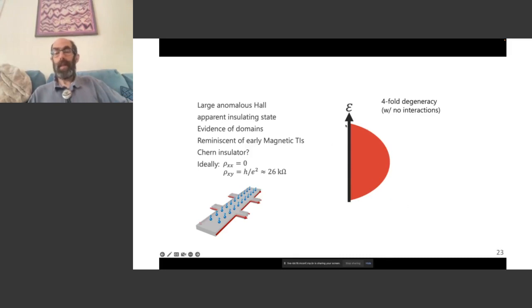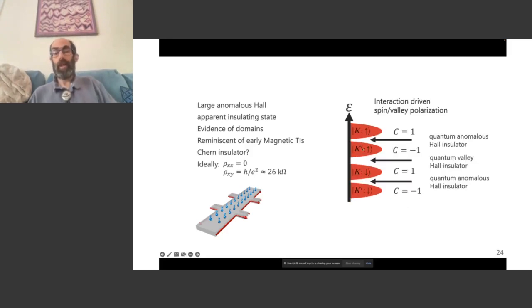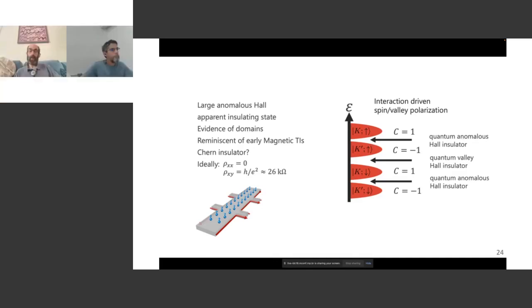So if you have a band that has a set of states that have this density as a function of energy and you fill it 3/4 full, nothing special should happen. It should look like a metal, a conductor. But if interactions cause this band to split into 4 separate bands, where you fill states with a particular spin and a particular orbital degree of freedom, fill all of those states before you fill the next set, then you could end up filling 3 of these and not the 4th. And then you might expect to get something that looks like a quantum Hall effect. And so that's what we thought might be happening based on our thinking and discussion with theorists.